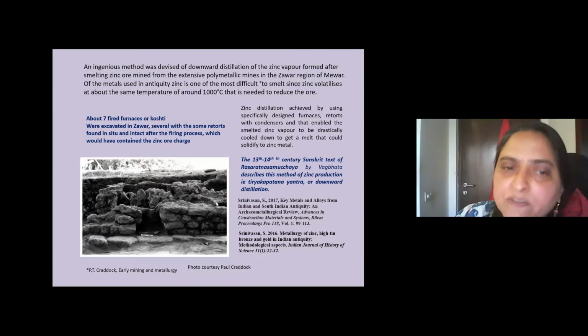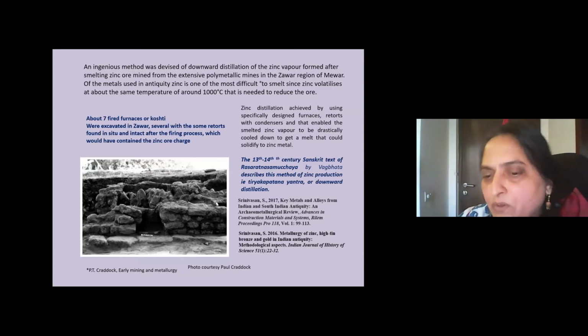And about 7 of these fired furnaces or koshtis were excavated in Zawar, along with numerous retorts which were found in situ, and these were intact after the firing process, and they would have contained the zinc ore charge. Now, what is also very interesting about the Zawar process is that this is one type of technology where there is a very good link with the textual evidence.